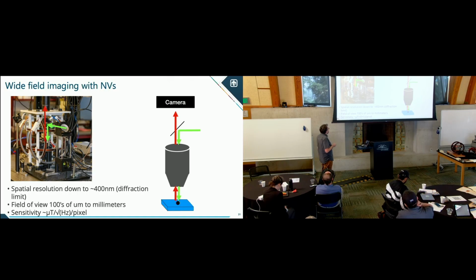So what we're doing in an imaging case is we have a microscope. This is built inside a Helmholtz coil to apply a small bias magnetic field. And inside there, we actually have, this is a horrific clip art of an objective that I made, where we pump it with green light and detect the red light, but we actually project it onto a camera. So instead of just projecting it onto a photodiode or a single photon detector, we have so many NVs in this diamond, about 4 microns of NVs at 50 ppm along the surface. We can actually see that red photoluminescence and sensitive enough for a camera to read out.